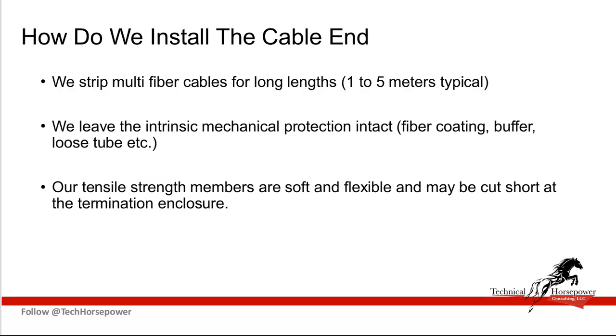Now, in an optical fiber, most of you know that's referred to as the fiber coating. In some cases, it may include a tight buffer, which is a directly contacted material between 500 and 900 microns in diameter, or in some cases, a group of fibers, maybe 12 or 24, inside a loose tube. And in general, the tensile strength members we use today are soft and flexible, so they are typically cut short at the termination enclosure at the entrance. So you have 1 to 5 meters of buffered fiber outside of that termination, and you don't want to have any damage from stripping the jacket or from pinching them, kinking them, etc., causing problems.